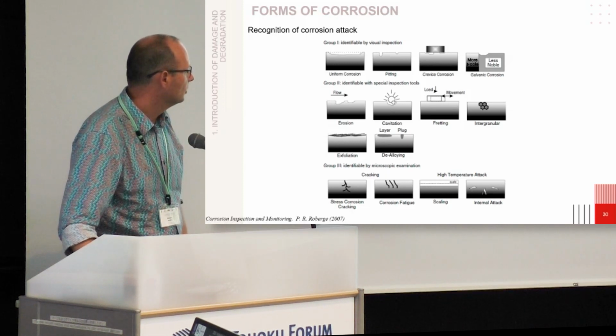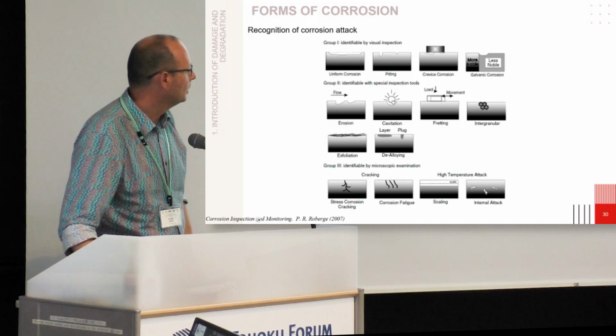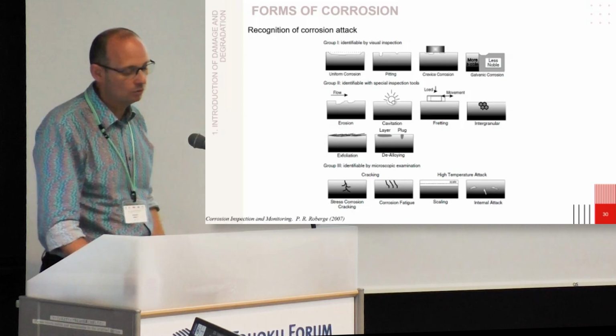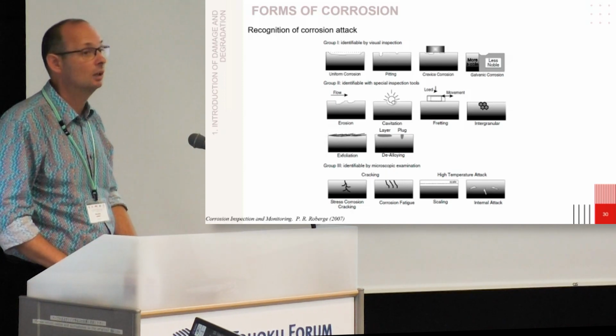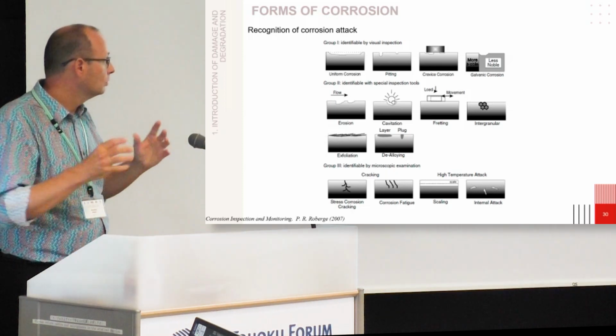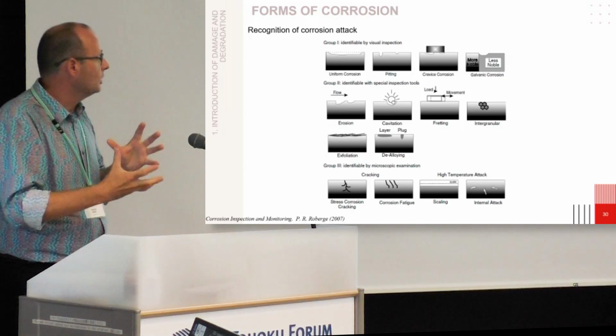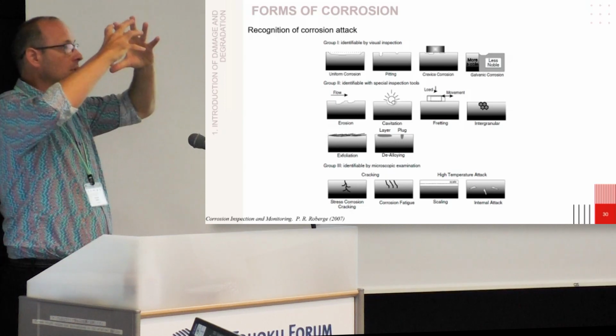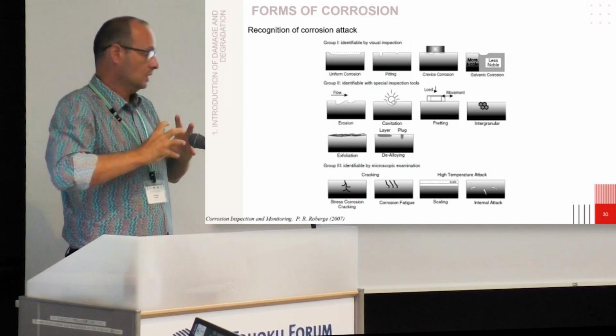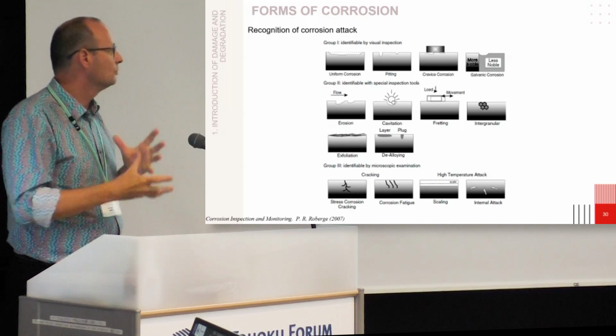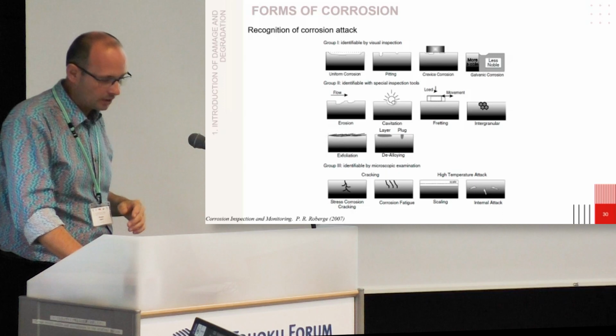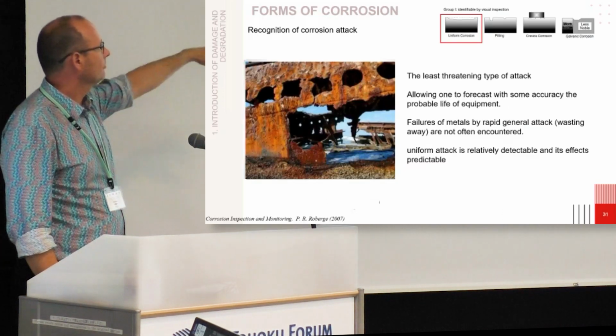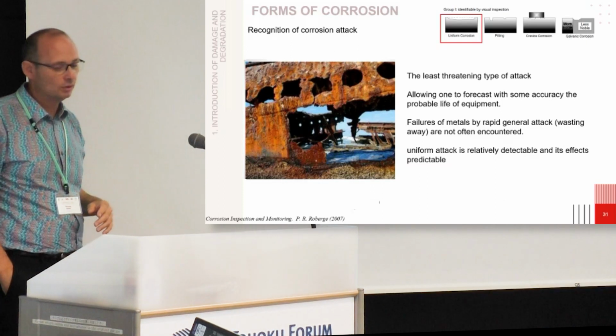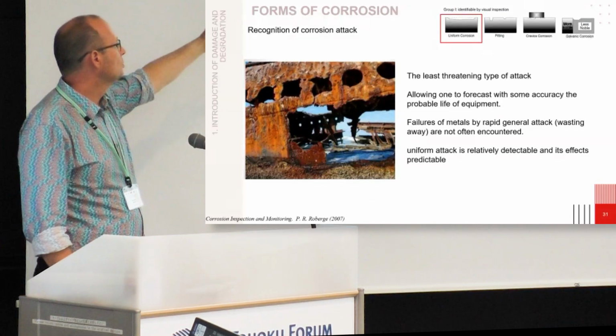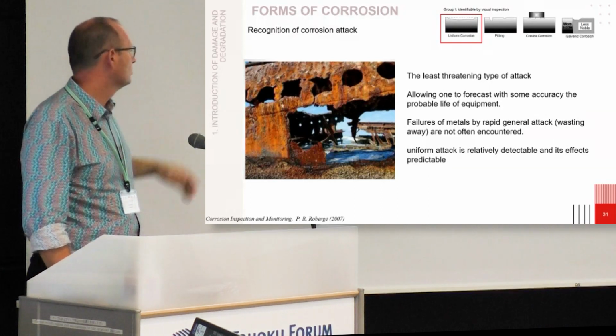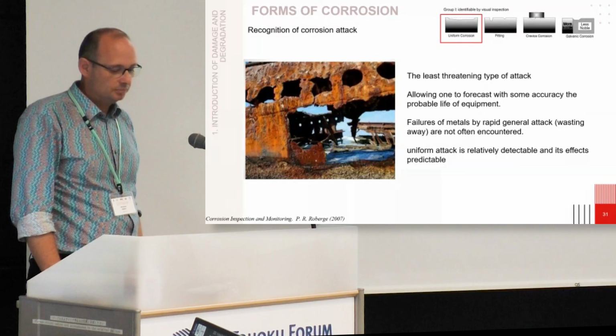I forget the name in English. This is quite important in the case of materials sensitive to hydrogen embrittlement. Actually, hydrogen will diffuse and make some pockets of hydrogen in the materials. As it's a gas, the structure starts to swell and you create some gas volume inside the material. Okay. Some details about corrosion. A beautiful picture of general corrosion.